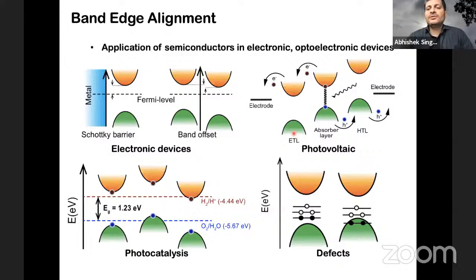Then when you are making a photovoltaic, you also need to know where all the different layers which you have, absorber layer, electron transfer layer, or hole transfer layer, where their VBM and CBM lie on a universal scale. So once you know this information, you can predict, okay, this material is good for the absorber layer, this material is good for the HTL or ETL. So these are very, very important information which one needs besides knowing the band gap, especially for a semiconductor. It also controls whether it's a good photocatalyst or where will be the defect transition levels. So I can't overemphasize the importance of this one parameter, actually two in this case, the positions of VBM and CBM at the absolute scale.